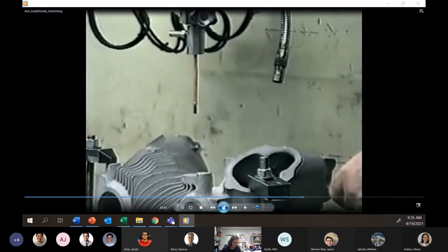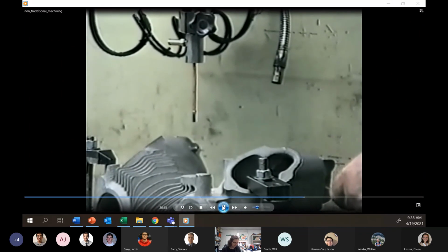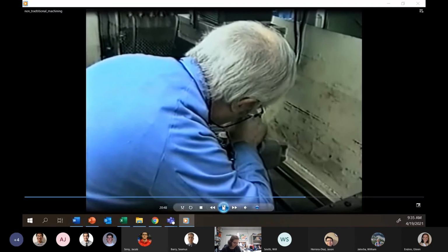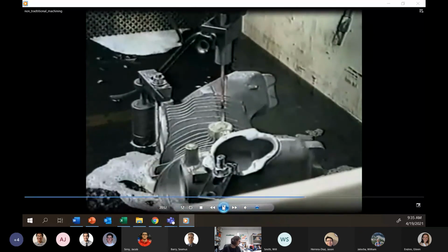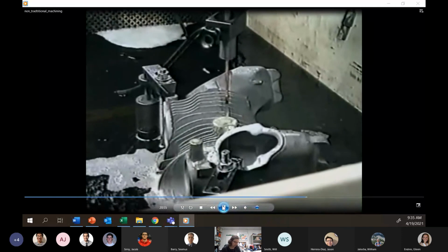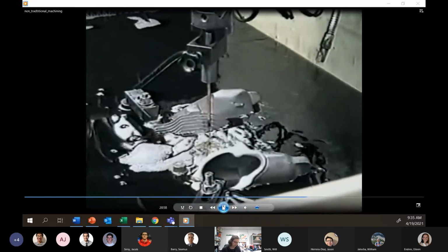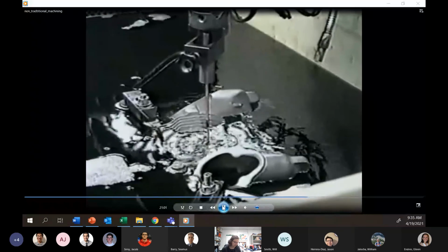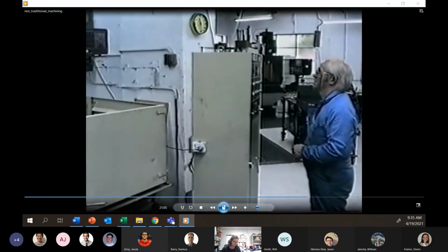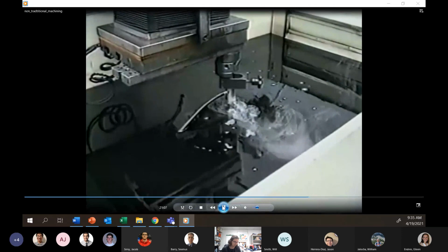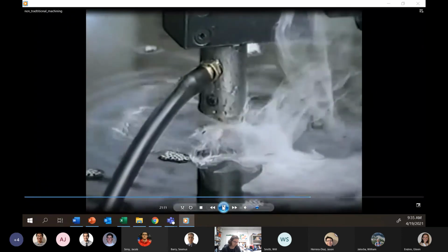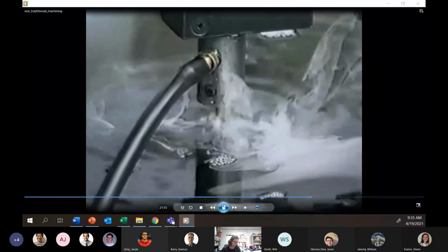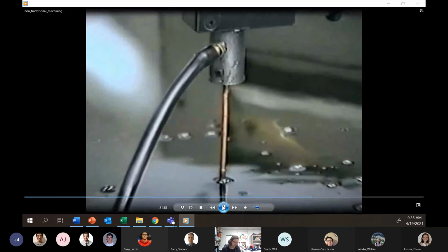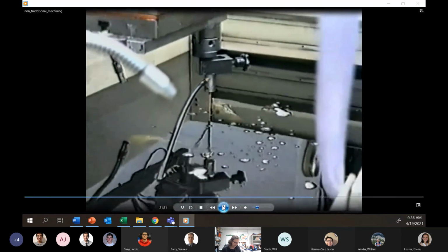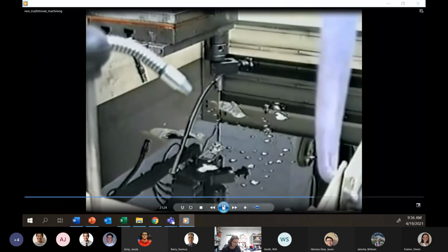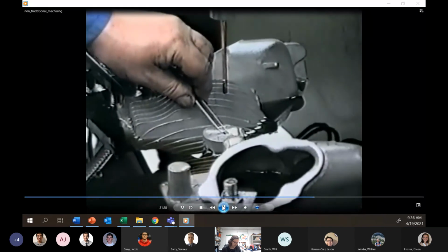Modern machines can automatically vary the power supplied as the area of the electrode changes during its cut. The electrode is lowered and then carefully aligned. The tank is filled with a dielectric light oil, some of which is being pumped out of the center of the electrode. This will later act as a flushing agent. Final adjustment is made to the controls to optimize cutting conditions. The broken tap is being machined away without damaging the surrounding material. After the tank has been drained, the remnant of the tap is removed.